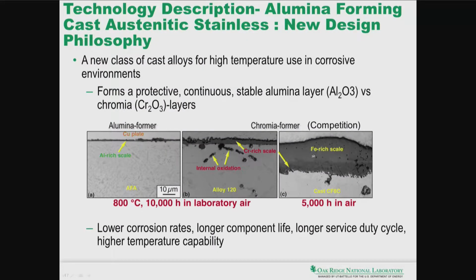So what is the design philosophy? The design philosophy in these alloys is to form a stable alumina layer, Al2O3, which is actually shown here in the alumina-forming alloys. You're seeing an aluminum-rich scale. This is in contrast to a chromia-forming alloy, where the Cr2O3, or the chromia, is the primary oxide layer that protects the alloy from its environment.